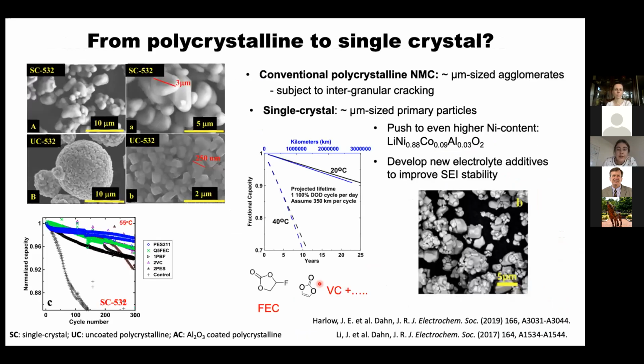And then the other point I think is important, particularly when talking to a material science department, is it's not just the chemistry, it's also the morphologies. If you look at the lithium cobalt oxides of this world, they're made of these so-called single crystals. And when people say single crystal in this field, they really mean just large micron-sized particles. But if you look at an NMC type system, then they're made of these large secondary particles, where the primary particles are maybe only 200 to 500 nanometers. And so that results in very different mechanisms for fracture and failure.